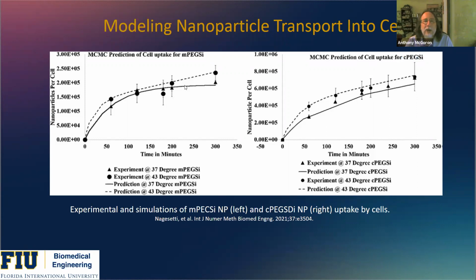We see a big difference in the cell uptake between the methoxy particles, much greater uptake with the carboxy particles, because the methoxy particles are completely neutral. The carboxy particles have some charge to them, which allow them to interact with the cell membrane. We also see really no difference between a normal temperature, 37 degrees and 43 degrees, compared to the carboxy PEG. We see an increase in the uptake into the cells due to the hyperthermia. So the importance of this study is twofold. One, to demonstrate, which has been demonstrated by other groups, the dependence of uptake into the cells on the surface functionalization of the particles. Also, whether or not we can increase uptake due to hyperthermia. And from these studies, we get some of the parameters that we need to further model in the three-dimensional spheroid.